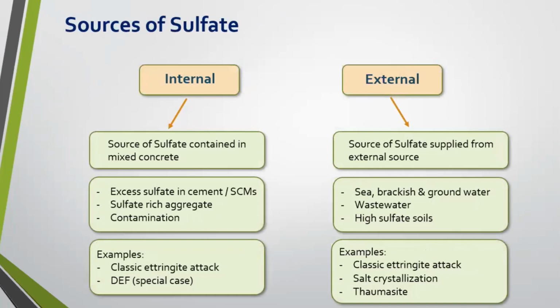So let's look at some of those sources of sulfate that might be problematic. When you're talking about internal sources, it can come from many different things. Occasionally, at least I think it's potential, I didn't see any documented cases of this, but if you know anything about cement production, you take cement clinker. On the back end, at the finish mill stage, you're adding gypsum along with some other additions. And it is possible to oversulfate cement. Again, I don't know of any specific cases where this led to later sulfate attack, but it is possible to have excess sulfates from that.